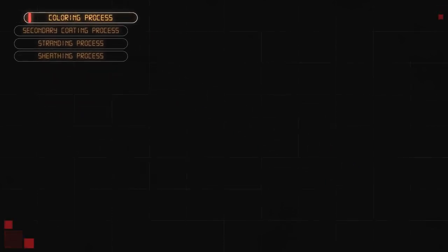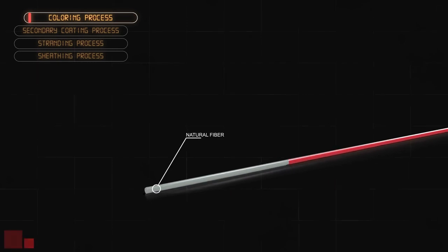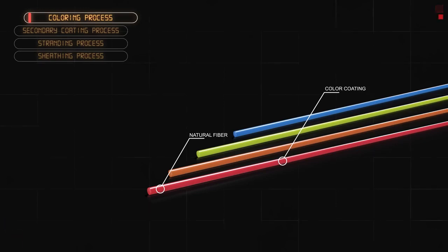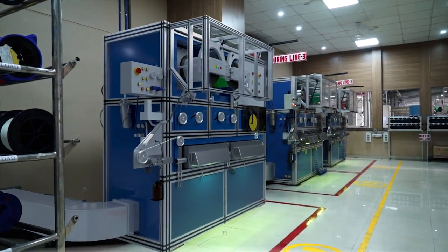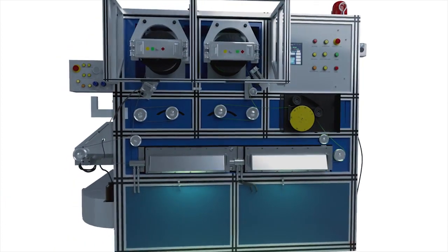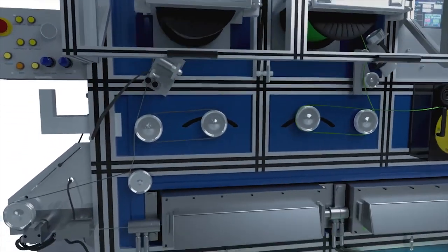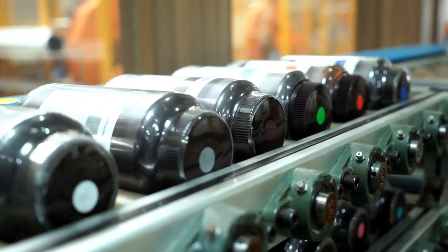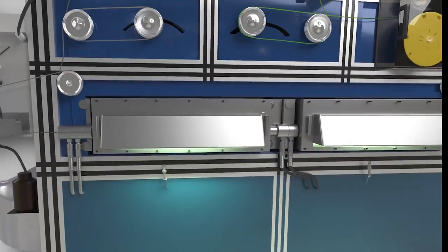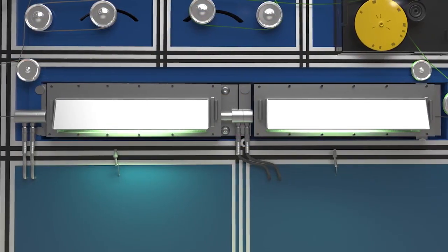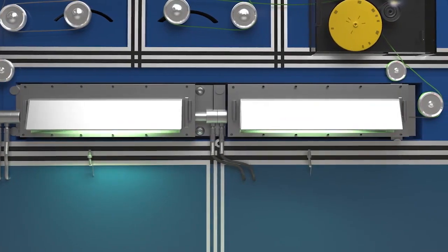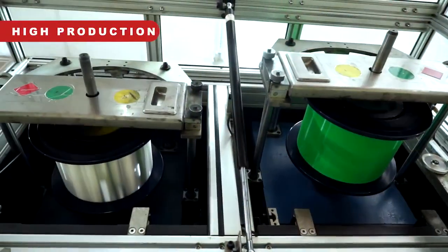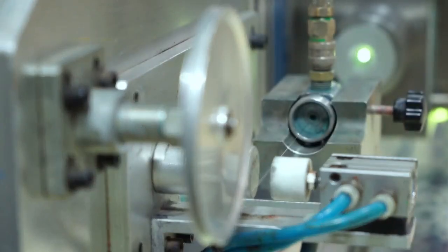Coloring process: The coloring process is used to color the natural fibers. The color identification of the fiber is required to splice fibers with same colors in field. In the process, the natural fiber gets passed through dyes. The UV curable ink is applied over the dyes. Finally, it passes through UV lamps for UV curing. Fibers cured with UV radiation are especially resistant to abrasion and scratching at high production speeds. This machine with high production speed is one of the most sophisticated coloring machines available today.